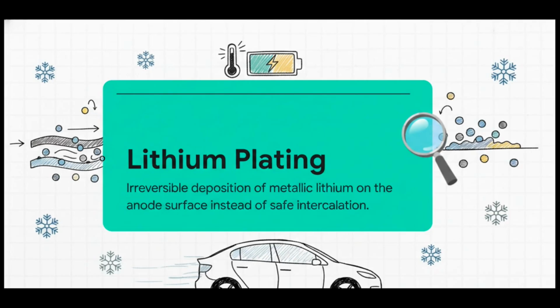When charging a battery, lithium ions are supposed to smoothly intercalate, or safely embed themselves, into the layered structure of the graphite anode. But in the cold, because that intercalation rate is severely limited, forcing a high current into the battery causes the ions to just stack up at the border. Unable to penetrate the anode, they irreversibly deposit as pure metallic lithium right on the surface.